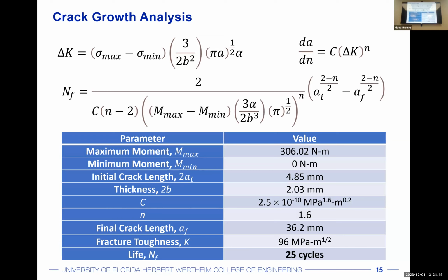So we were able to calculate a range of fracture toughnesses as well as the rate of crack growth, and then bringing all of that together along with the material properties in order to determine that even with a crack at our rivet holes, we could still see a life of 25 cycles. And this was also the range that we were looking for, again, assuming the sizes of the regolith that we would expect to impact our lander.